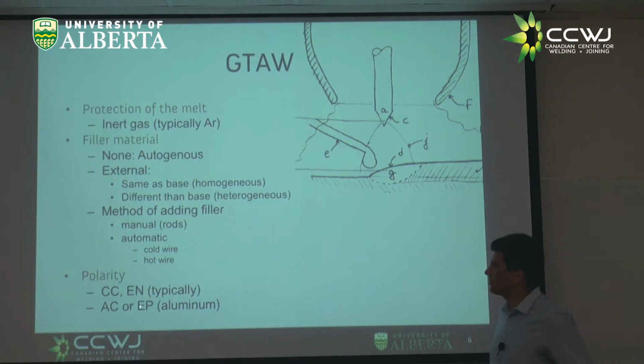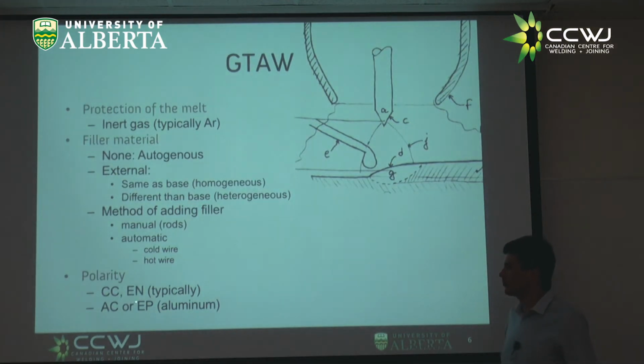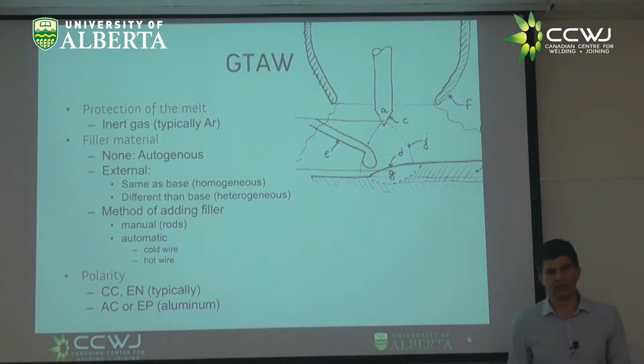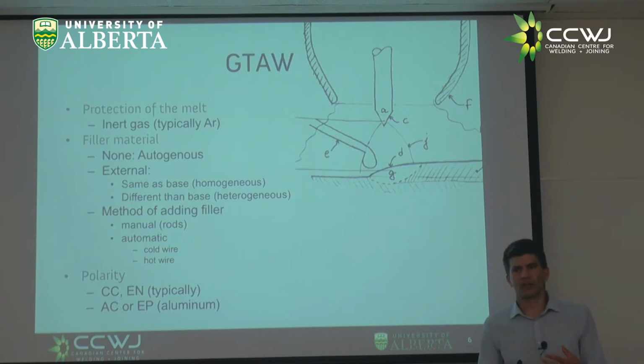Other things, in aluminum, sometimes you have AC, electrode positive, very, very seldom. It's only if you have no other way. But AC means alternating current or variable polarity. And you're going to see in the lab what happens with aluminum. Aluminum oxidizes. What happens is it has this protective oxide layer. Now, when you weld, what you weld is the metal, not the ceramic oxide layer, right? So the oxide layer is your enemy.